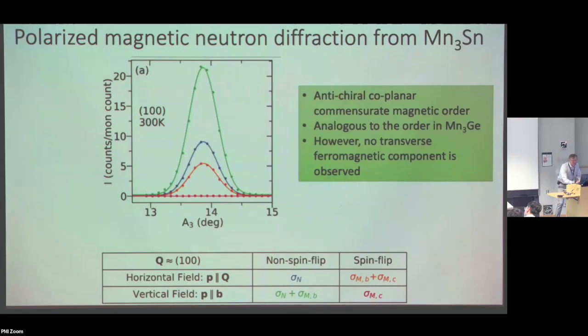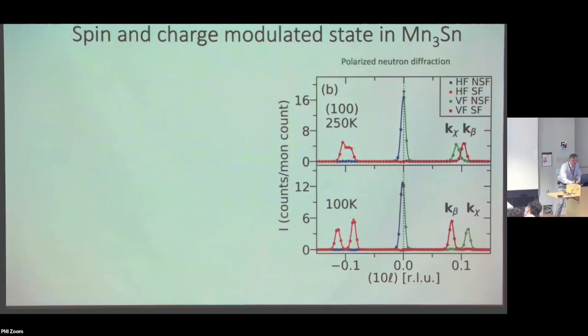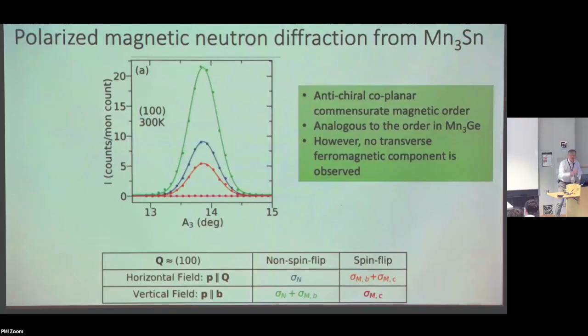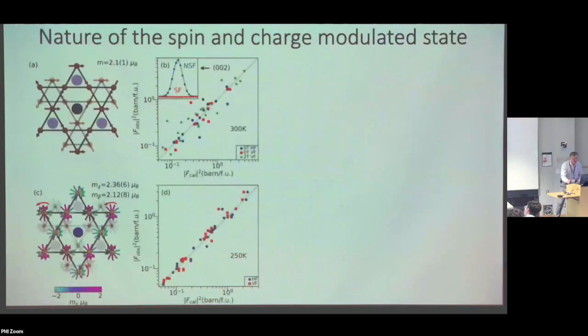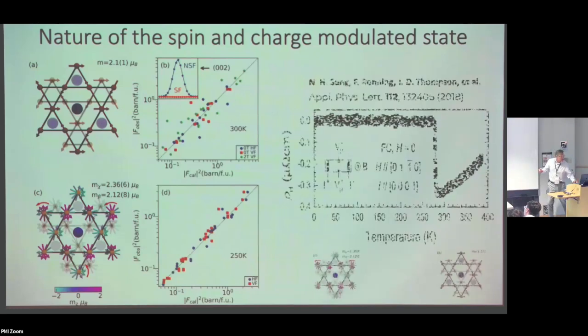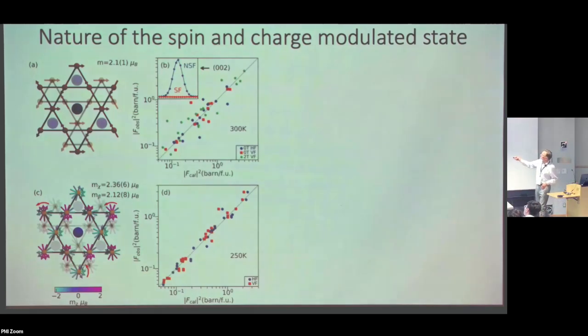So then, let's see. Then we now go to the low temperature state. So this material is kind of the other way around. It has a commensurate structure at high temperatures, then an incommensurate structure at lower temperatures. And maybe I should say, by showing this, I should show what the commensurate and incommensurate structure look like. So this is the commensurate structure.